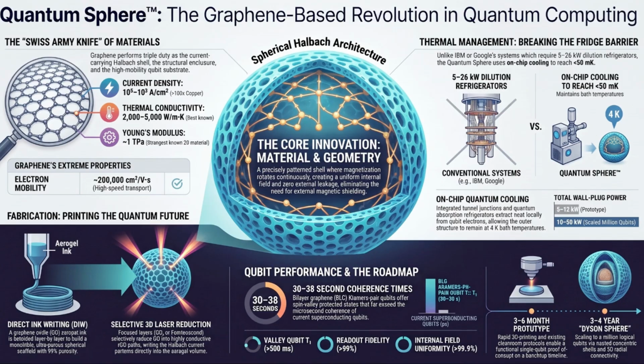The white paper outlines a two-step printing and reducing process. Step 1 is direct ink writing, or DIW. Direct ink writing is essentially highly precise robotic 3D printing. You take this yield-stress graphene oxide ink and extrude it through a microscopic nozzle about 400 microns wide onto a platform. But this isn't a normal printer bed. The platform is supercooled to negative 25 degrees Celsius. So you are printing layer upon layer of this wet hydrogel to build the hollow sphere, but because the platform is freezing, the water inside the ink is freezing into ice the moment it touches down. Right. You're essentially printing a sphere made of frozen, microscopic, muddy ice.